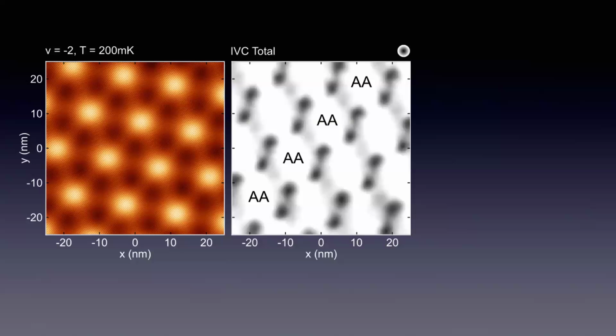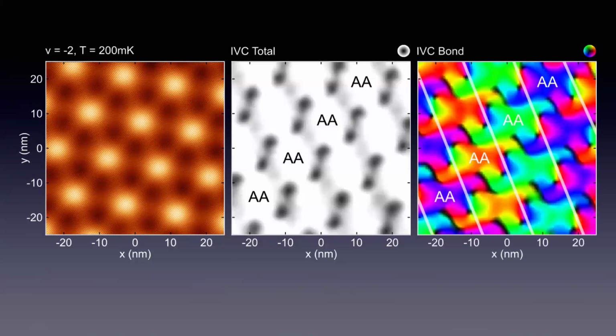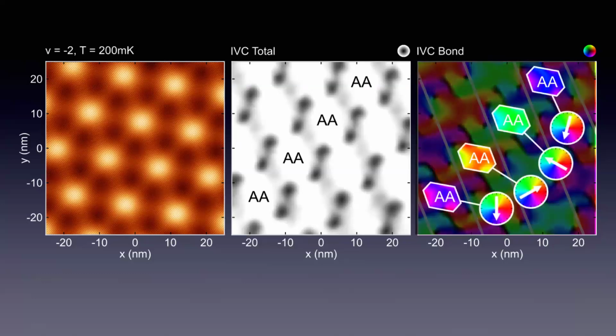Now what I'm showing you is one of the order parameters, IVC total. This just represents the total order parameter of having any kind of IVC order. So that's its amplitude. You notice that it's positive almost everywhere, with some spots where it's suppressed. And then you look at the phase. Now you realize why this was such a hard experiment, because the phase is actually changing in real space. It looks very psychedelic, I know, but if you just focus in, you can see that it's going through phase rotations about every 3 moiré units. So this is an electronic phase that breaks a symmetry, not just on the graphene scale. It makes an order parameter, and that order parameter can break the symmetry on the moiré units.